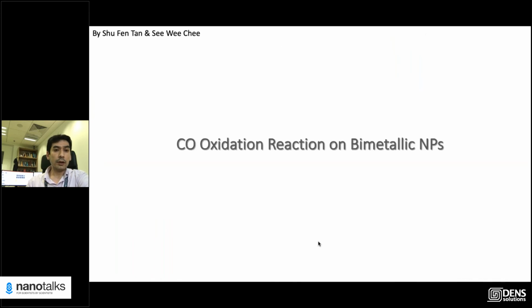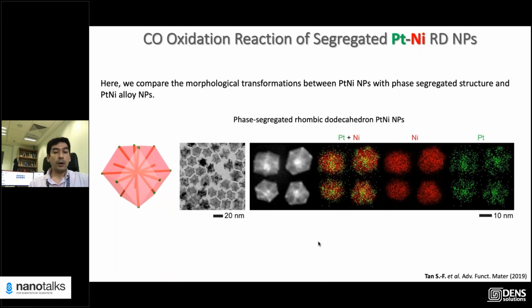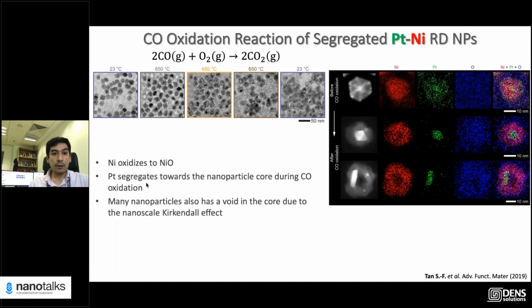Since I started with the bimetallic nanoparticles, you can actually look at different types of bimetallic nanoparticles and see how they evolve during, again, the model CO oxidation reaction. This is a nanoparticle where a platinum frame is segregated from the nickel body of the nanoparticle. We synthesized it so it has rods of platinum embedded in the body of nickel. And what you can do is really see how the transition is happening.